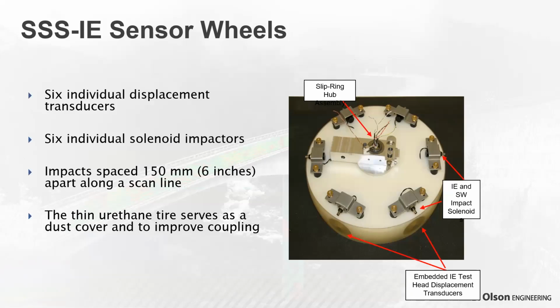Each sonic surface scanner has two wheels, each with six transducers and six impactors, similar to the impactor and transducers in our other impact echo devices. They do a test every 6 inches along each test path. Since you have two wheels, you get a set of tests every 6 inches alternating between the two wheels. So you're doing two paths at a time with each pass. The transducers themselves are coupled to the concrete through a urethane tire that serves as a dust cover. It's a wear cover. It also helps to improve the coupling.